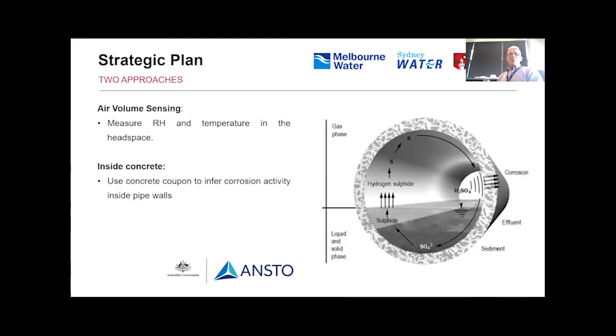So this resulted in two strategic approaches that we have invested in. One is having sensors that can be deployed in the air volume of these wastewater pipes, and I'll talk a little bit about those in the next few viewgraphs. But with respect to inside the concrete, we knew it was never going to be feasible that contractors could be trained effectively to install these inside the concrete in a fashion where the calibration will be meaningful. So we've taken an approach: we're going to use smart concrete coupons as almost a sacrificial corrosive feature that will be bolted on the inside of the concrete pipe.